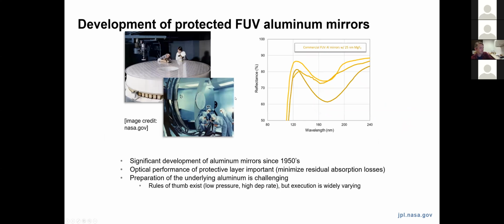Okay, so just a brief background on protected aluminum mirrors. So again, this is a very simple optical coating. It's a single layer of metallic aluminum, which, as I showed a few slides ago, in a perfect world would have extremely high reflectance in the far UV because of its high plasma frequency. The free electron nature of aluminum that gives it that high plasma frequency also makes it quite reactive. So it has an extreme tendency to oxidize, even in fairly high vacuum environments. And that oxide, unfortunately, is strongly absorbing in the far UV. So an unprotected aluminum layer does not make a very good ultraviolet mirror.